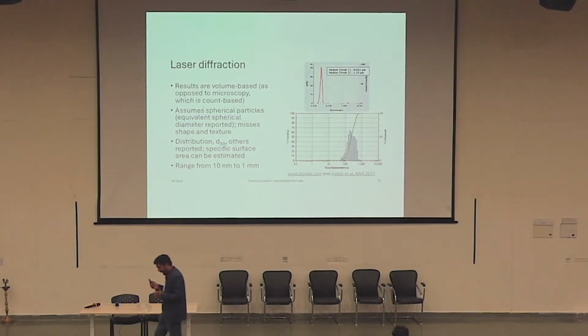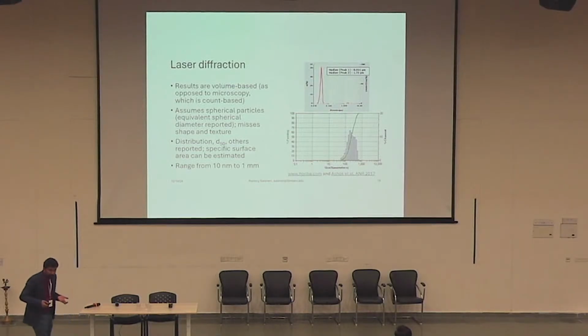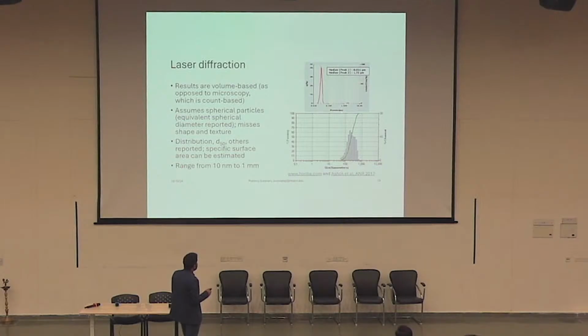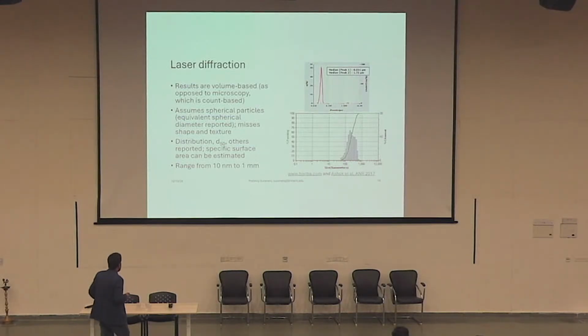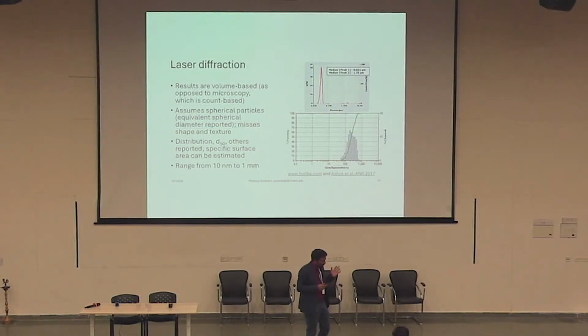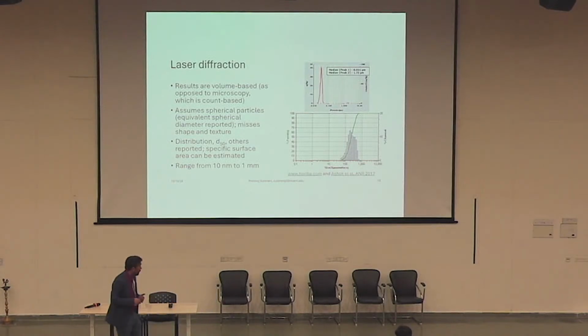You completely miss texture. If you've developed very, very textured particles, the size that you get or the shape that you get from this test is potentially misleading. This is an example where they used laser diffraction, where most of the sample was fantastic, but then they had this small impurity or something which turned out to be pretty important, and that was at a larger range, right? So this may not have been caught using some other techniques, but because this technique spans a pretty large detection range, they were able to find it. So the range is typically 10 nanometers to about 1 millimeter, but again, depending on exactly which instrument, which configuration you have, you can go left or right just a little bit.